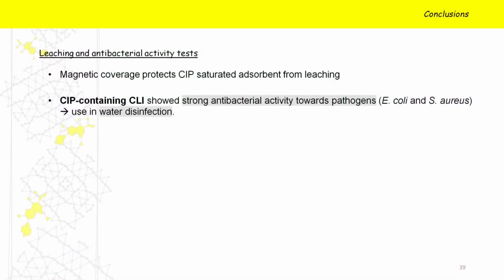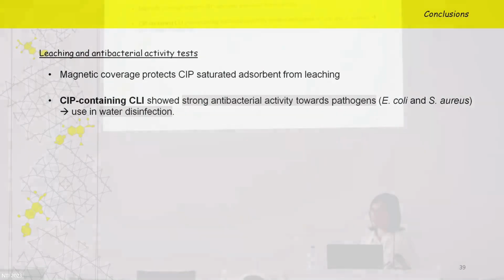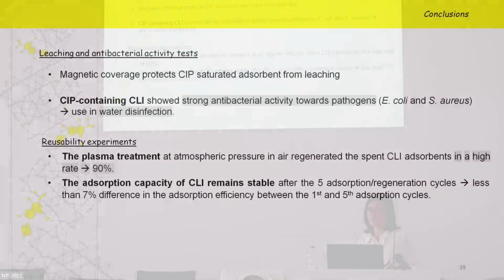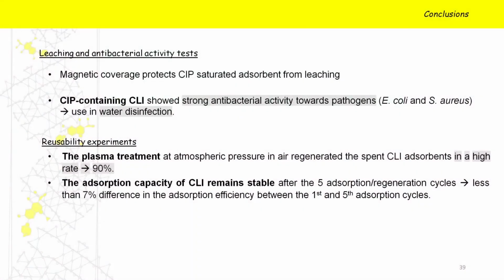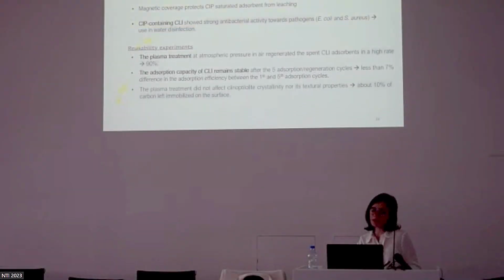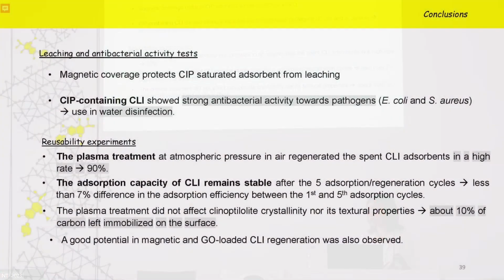The leaching and antibacterial tests show that the magnetite coating prevents clinoptilolite from leaching, and that there is a possibility to use the spent adsorbents in the disinfection of water. The reusability test also showed a high rate of regeneration, and we can say that plasma is a potentially good, innovative and novel treatment for the regeneration of spent clinoptilolites.